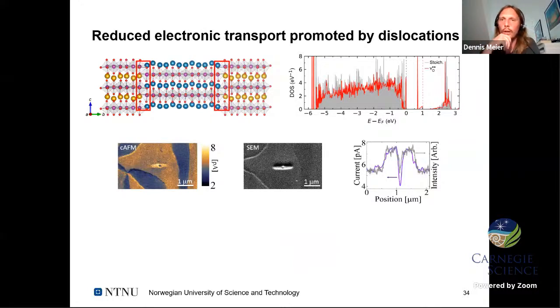But of course, we wanted to control conductivity. And that's why we also looked into the transport properties. And it turned out that these dislocations also have bound charges. And because of that, oxygen vacancies like to sit at these dislocations. The oxygen vacancies induce more N-type carriers in our P-type system, they recombine, we end up with less mobile carriers, and that's why the conductivity at the position where we induce a lot of these dislocations drops.